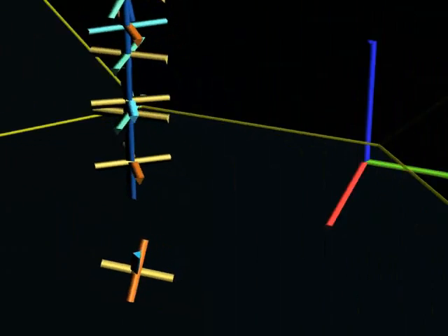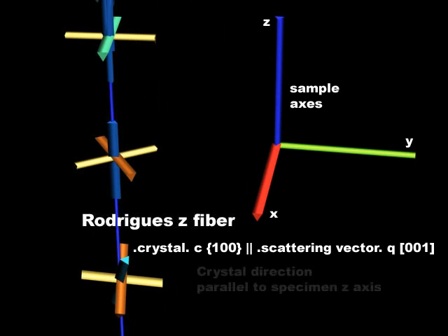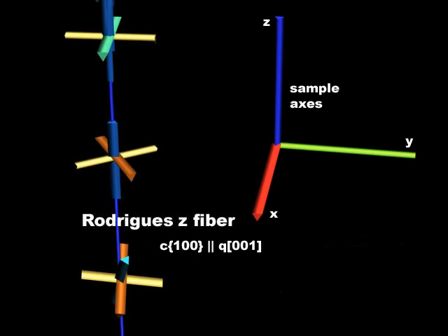The cycle repeats for many directions in the sample. The jacks on the Rodrigues figure show lattice strains for crystals having a 001 crystal direction aligned with the sample z-axis. Again, color of each leg indicates the magnitude of the principal strain value and the orientation of the leg indicates its direction. Individual jacks correspond to strain in individual crystals.